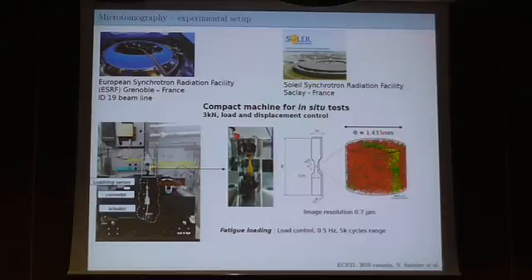The reason why we look at such a small volume is that the image resolution we are seeking is 0.7 micron. So you cannot have a large volume image. You need to have a very focused area. Our fatigue loadings were load control at 0.5 Hz, and the result I show you today is in the 5,000 cycle range.